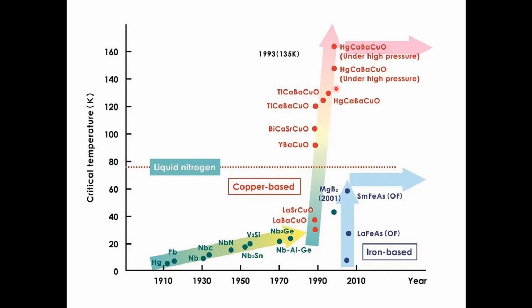But the interesting thing is that if you put higher and higher pressure, so this is a mechanical high pressure, it will increase the critical temperature by could be 20 Kelvin, which is quite a lot. So this is quite an amazing technique to make one material become even more of a superconductor with higher critical temperature values, okay?